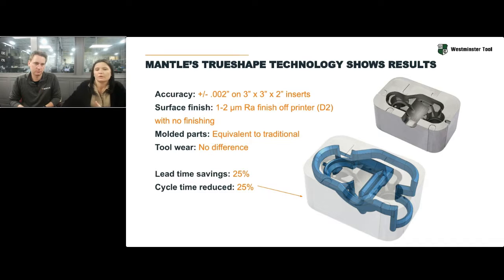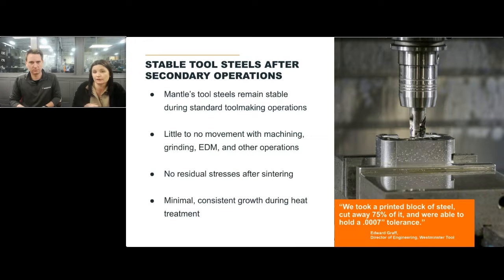Really, once we got into this example, the biggest thing that sold us was the stability. Off of the printer, we were able to go in and do whatever finish machining we needed to do with little to no movement. There weren't any stresses left over. With Mantle's process, they're sintering partially along the way, so the final sinter has a much smaller shrink rate, which results in a much more stable, less warped product, which was huge. And ultimately, it was why we invested in it.